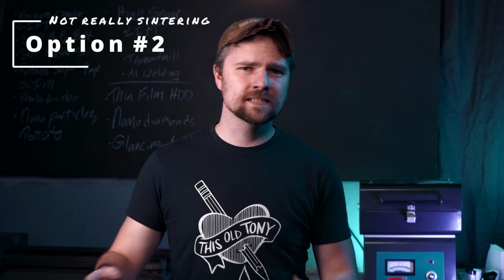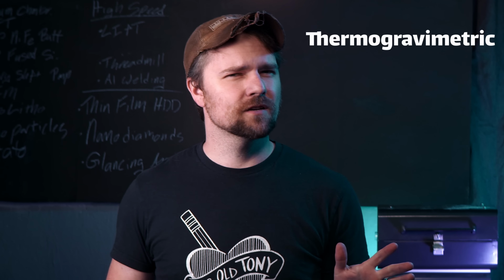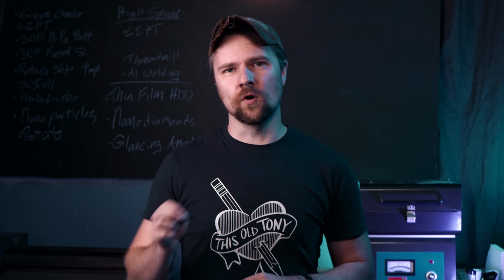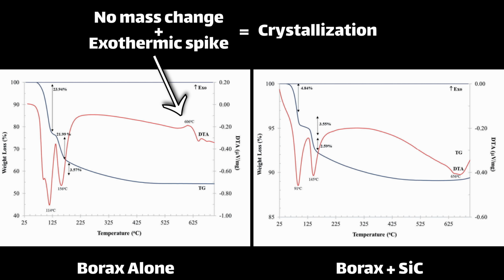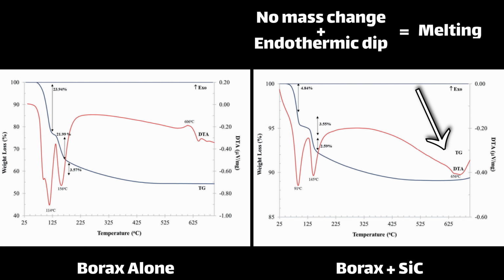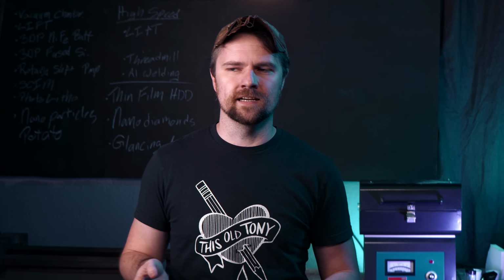So that's option 1. Option 2 is that there is little to no oxidative bonding between the silicon carbide grains. So that proposed mechanism of glass forming in between the individual grains is not actually happening, or not enough to really do anything. The paper does do thermogravimetric analysis of their samples to see when or if the borax crystallizes by itself or in the presence of silicon carbide. And that data is fairly convincing that the borax isn't crystallizing on its own to make a crystalline network. So it's likely just amorphous borax kind of hanging out there.